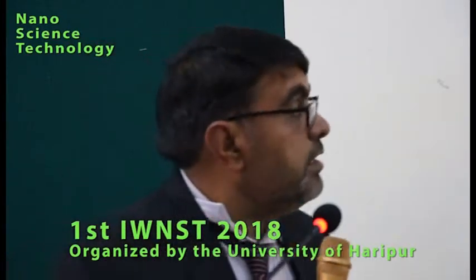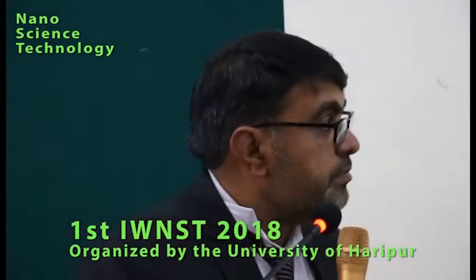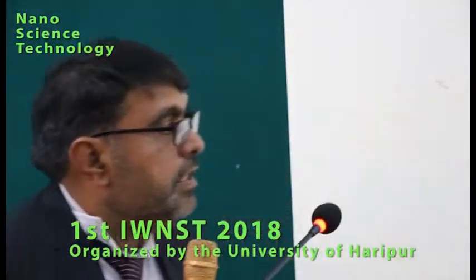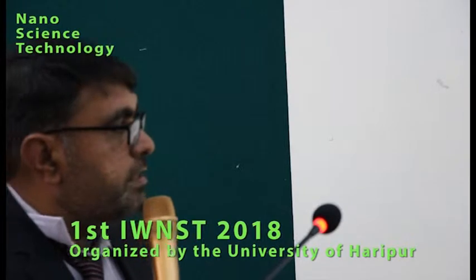And these are the results for the nickel complex and aluminum complex. Again, we see when we move from monometallic system to bimetallic system, the surface morphology is greatly improved, and also the decomposition produces nanorods. Here are some XRD and other results.